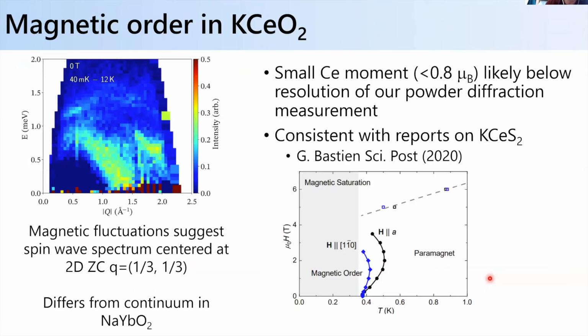Not the dipole-octupole doublet. And in fact, we can do inelastic neutron scattering on the system at lower energies, and we see indications of what look to be well-defined spin wave excitations coming out of a zone-center position, suggestive of a ground state with spin wave modes, and we're just unable to resolve the magnetic Bragg scattering because the background's too high, and there are limits on neutron powder diffraction in terms of the size of the ordered moment you can resolve. So basically, this spectrum differs from the continuum we see in NaYbO2. We think it's indicative of a very weak magnetic order below this T star transition that we just can't resolve in our neutron diffraction measurements.